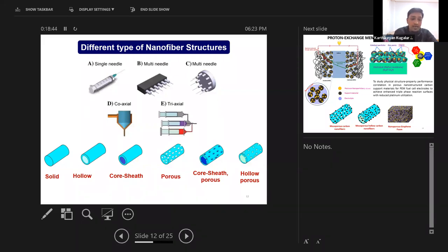For example, if you use a single needle, you are producing a solid nanofiber. If you use this coaxial setup, there will be a mixture of two nanofibers. Inside this part, there will be one solution, and the outer part will have another solution. This is called a coaxial setup. The inner solution and outer solution will combine here, and it will form a fiber like this, a core-sheath nanofiber. If you eliminate this core part, you will get hollow nanofibers. This porous nanofiber, you can create by mixing with certain materials, and you can leach out that material by using a thermal or solvent-based technique.